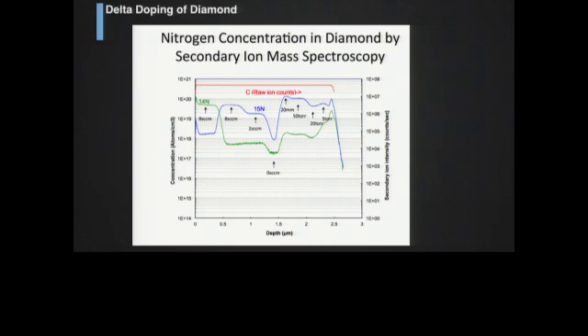One of the problems that we were worried about is that nitrogen 14 and doubly ionized silicon have the same charge to mass ratio. So we put in nitrogen 15, and we've been able to change the doping over a fairly wide range by just changing the concentration of the nitrogen in the material. So this is a single layer that we grew, and these are all the different pressures, flow rates of the nitrogen 15, that we grew it at.